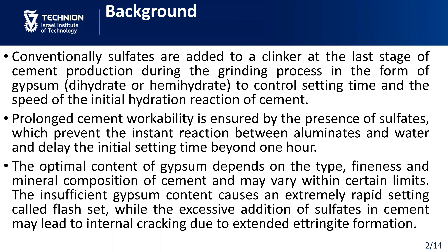Usually, sulfates are added to a clinker at the last stage of cement production during the grinding process in the form of gypsum, to control setting time and speed of the initial hydration reaction of cement. Prolonged cement workability is ensured by the presence of sulfates, which prevent the instant reaction between aluminates and water and delay the initial setting time beyond one hour.